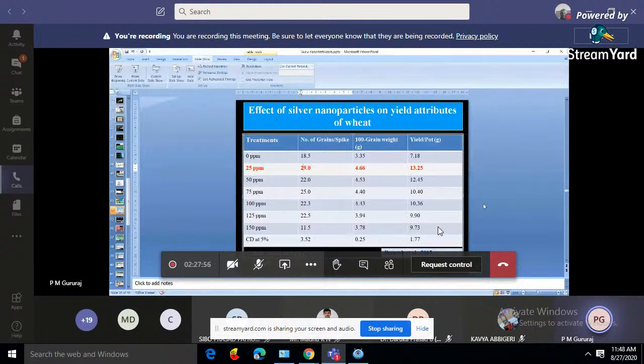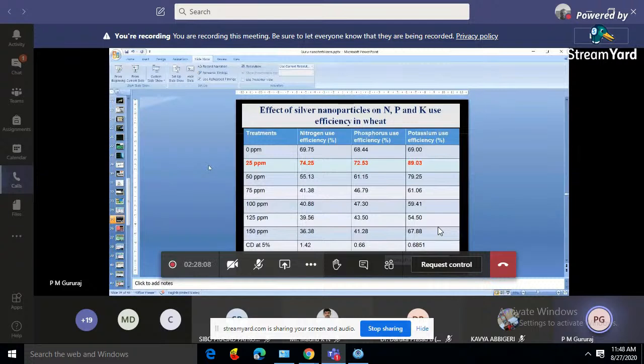Again, this is the content of nitrogen, phosphorus and potassium. So you can see 25 ppm actually works very well for nitrogen efficiency, phosphorus efficiency, and potassium efficiency. The others keep on decreasing, and no nanoparticle is also lesser. If you use no nanofertilizer, you get 69.75 nitrogen use efficiency, while with 25 ppm, you get 74.25. Similarly, phosphorus use efficiency increased, and potassium use efficiency also increased. That means nanoparticles are definitely helping the plant to use its nutrients well, and also give better crop productivity, and also it is disease free. That is what I want to say in that.